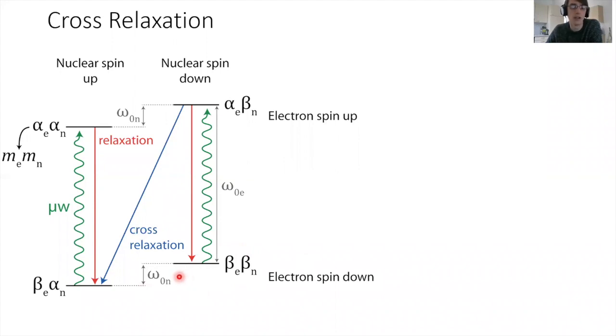Then we irradiate with microwaves, that's the green wiggly lines, and we populate these upper levels. Now this is a higher energy arrangement. It wants to relax back to equilibrium, and it can do this via single quantum relaxation. That's the red lines. And if that happens, nothing's really changed. What can also happen is we can get zero quantum cross-relaxation. That's this blue arrow. And that's when we simultaneously flip an electron spin and a nuclear spin in a sort of flip-flop.